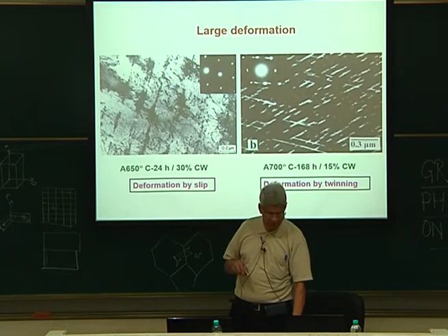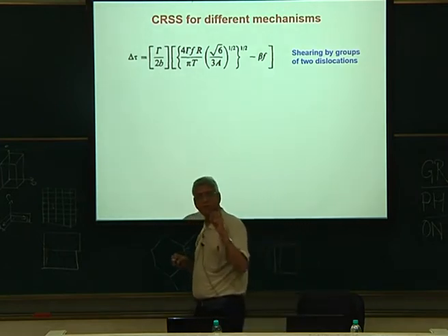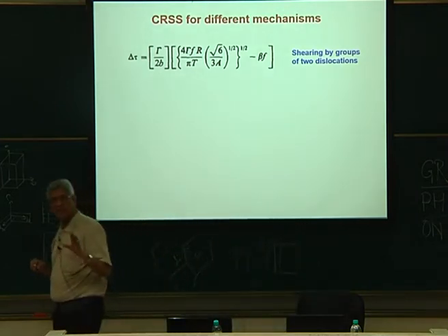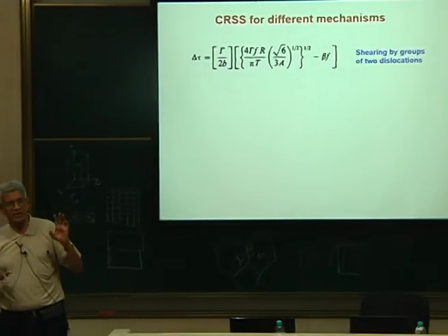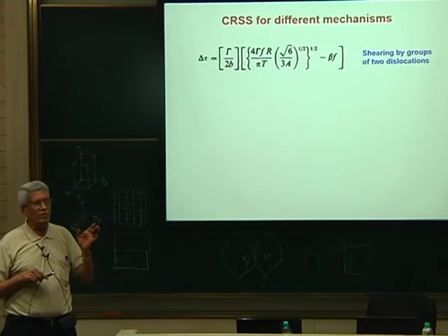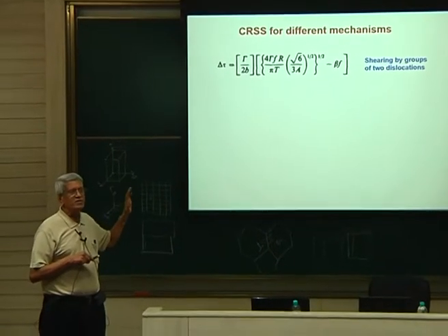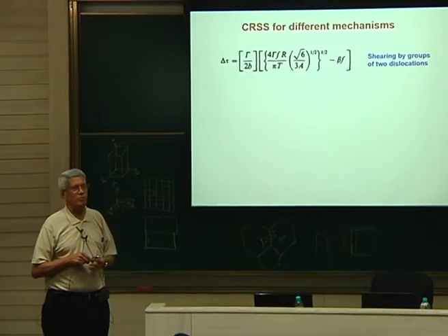So the general concept that the mechanism changes from shearing to looping as the particle size increases is valid only for materials where the stacking fault energy of the precipitate is very high. When the stacking fault energy is very small, instead twinning is the mechanism which forms.